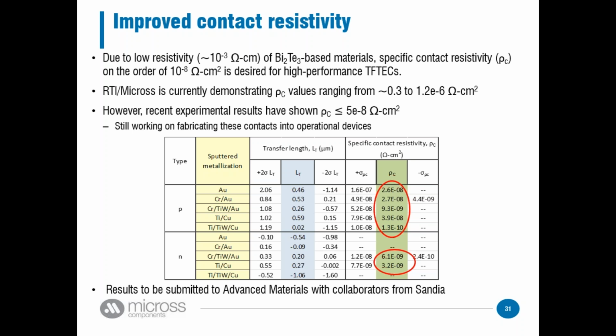Fortunately, we have been able to demonstrate that on test structures. We use a TLM transmission line technique to put a series of sputtered metal contacts onto the material. We normally would use electroplated or evaporated contacts, but in this case, we developed a technique to put sputtered contacts down. And again, we're seeing the type of contact resistivities that we need to get the results. We've worked quite a bit with Sandia, who's another performer on the DARPA Matrix program, in order to get this to work. And we've just finished up a manuscript and submitted it to Advanced Materials.